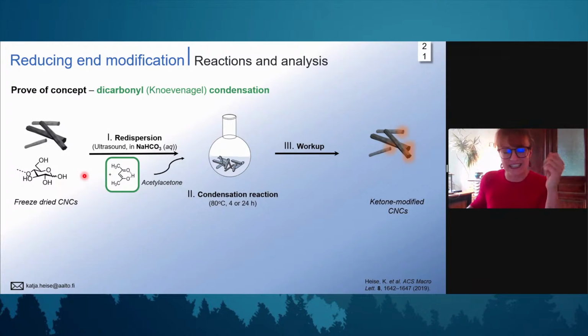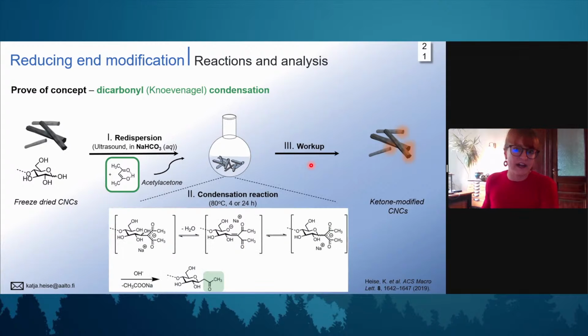You can also translate this to other dicarbonyl compounds. The condensation reaction is carried out at 80 degrees overnight, and then you have a very simple workup just with water and by dialysis to obtain the ketone modified cellulose nanocrystals. The reaction itself goes over several intermediate stages, and the only side products that you have are water, of course, it's a condensation, and also sodium acetate. So the aqueous workup is really easy. And what you end up with, as I mentioned, is the keto functionality on your cellulose nanocrystals.